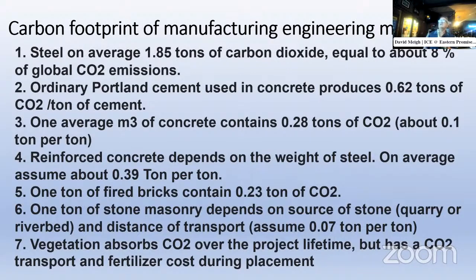So about 10%. Reinforced concrete depends on the weight of the steel. On average, we can assume about 0.39 tons per ton of reinforced concrete. 1 ton of fired bricks contains 0.23 tons of carbon dioxide. 1 ton of stone masonry we can take from the quarry or the riverbed, and the distance of transport depends on it, but we can assume 0.07 tons per ton.